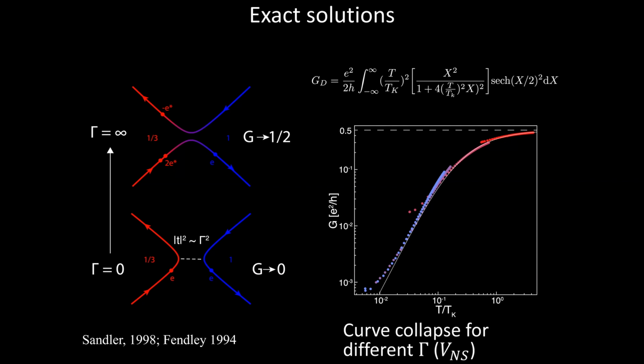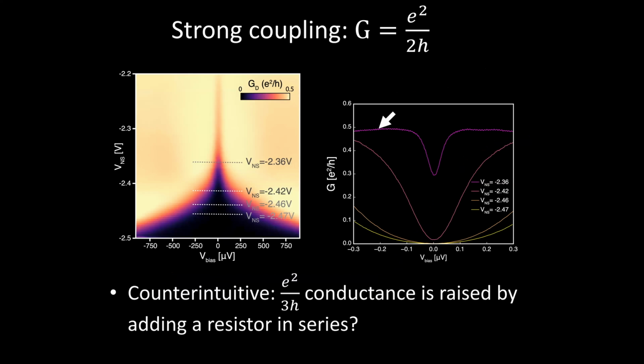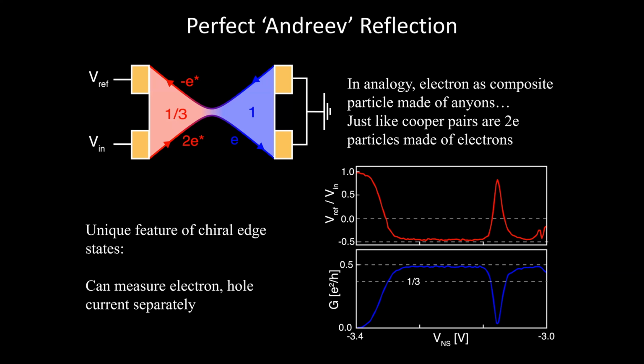But in the fractional quantum Hall context, you can actually measure the currents and voltages on each of these limbs of this point contact. So for example, since I'm running out of time, I'll do this quickly. You can inject voltage here, which will inject some current, and you can measure the voltage that's reflected. And you see that if you put a volt here, or more likely a millivolt, you'll get minus half a millivolt on the other limb, which is just coming from the fact that every time you put 2e in here, you get a negative current in order to get 1 electron across the junction to the other side. So what you're seeing is this retroreflected charge.